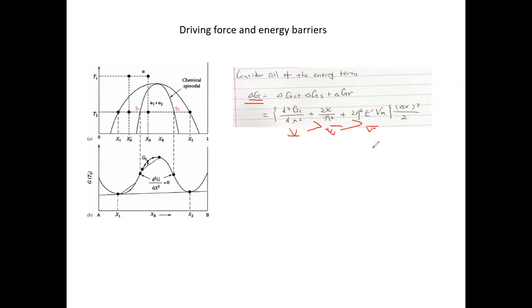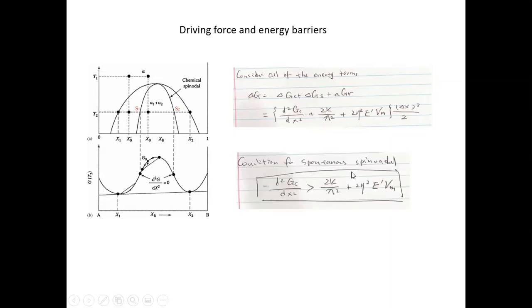So this is the change of free energy for all compositions. Starting from the beginning, you only have the first term, and as the system starts to separate more and more, you start to have contributions from the second interface term and even the bulk mismatch term. But this equation holds for all composition differences. Now, if we have this, we can write down the condition for the spinodal to occur. If you want the spinodal decomposition to occur spontaneously and continuously, you don't want to initially start the separation happily but get stuck at some stage when the interface begins to play a more important role, or eventually the bulk dominates.